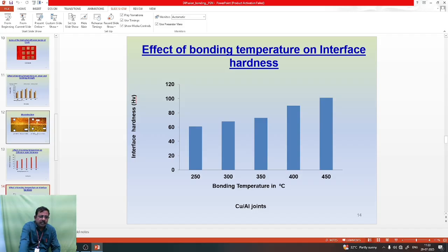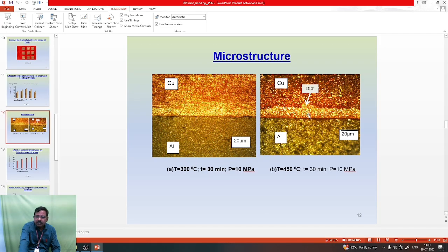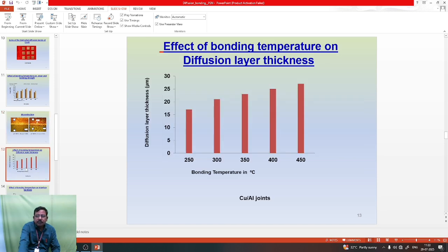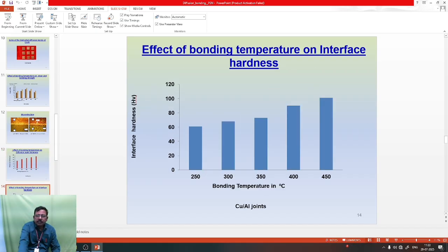The effect of bonding temperature on the interface hardness. Okay, here the interface hardness depends upon the bonding temperature. The interface hardness, that is a hardness which occurs between the metals. Look at here. Here this is a diffusion layer thickness. This is called the interface. The interface depends upon the bonding temperature. When the temperature increases, the interface hardness will be higher.